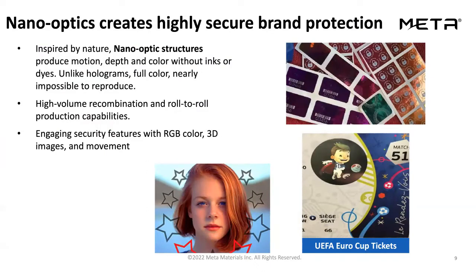In terms of the application space, one of the products that we have currently is what we call color optic, which combines the micro and nanostructures to create this depth and color and motion. What we see here in these pictures, we don't use any inks or dyes. These are purely plasmonic elements, so truly metasurface metamaterial elements, and we can tune the structure dimensions, the height, the diameter, the pitch, and shift the resonant absorption, which defines the security features that we use for RGB colors, and then create these 3-dimensional images, which you only see here in 2 dimensions. And this basically provides us ultra high resolution, which is impossible to reproduce using other methods.